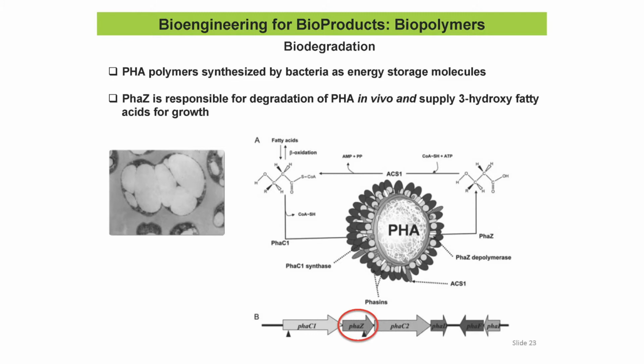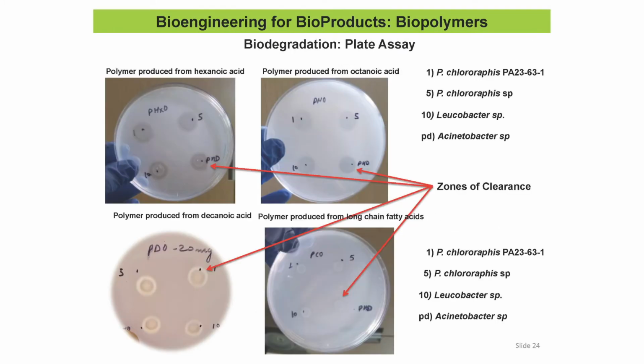And it's one of the many proteins. These granules consist of the polymers surrounded by a membrane, and there's a bunch of proteins embedded in the surface. Amongst these, the PHA synthase that synthesizes the polymer, and the PHAZ depolymerase that depolymerizes it when it wants to use it. So we developed a plate assay where we made colloidal plates of polymers made from different sources, from hexanoic, octanoic, decanoic, or long chain fatty acids. And we screened a bunch of bacteria to see if they could grow on those polymers.